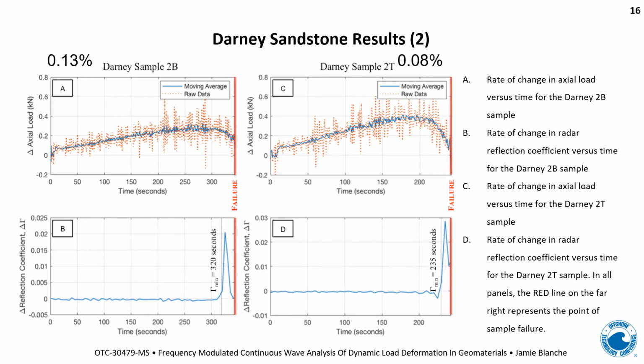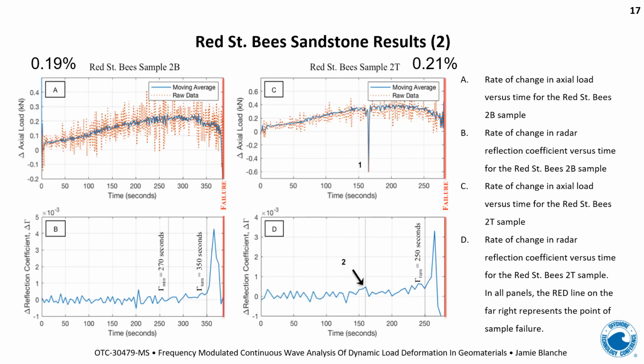Now, what's important again to notice is that for the change in reflection coefficient, everything's constant right up until you get this runaway change in the reflection coefficient, which is consistently in advance of the failure point. So again, in keeping with the previous slides, we're seeing very much the same story for the Red St. Bees sandstone. We're seeing an increase in the rate of change. We're seeing a peak in the axial load that's in advance of the runaway spike for the reflection coefficient.